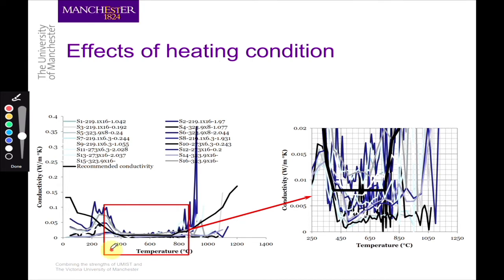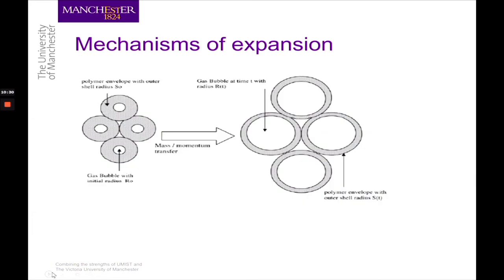As you can see in this region, which is of course the most interesting, most effective region of fire protection, the thermal conductivity of intumescent coating varies hugely, by almost orders of magnitude. And that's really important. We can't simply use some sort of average temperature-thermal conductivity relationship. We really have to understand the expansion mechanism. And that has been what we've been doing for some time.